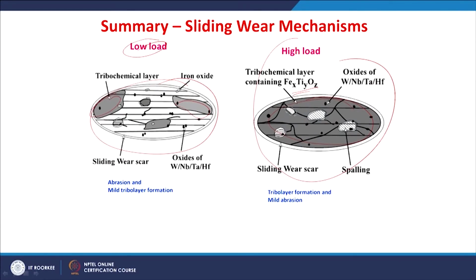So, the process is like this: in the initial conditions of sliding, the deformable material or the nickel binder phase comes out, smears out and deforms, followed by the cracking of these ceramic core and rim phases. So, at lower loads the oxidation or abrasion is dominant; at higher loads, the oxidation of this debris will lead to a compacted layer which is rich with the iron titanium oxide, because it fills the entire surface, and then it reduces further wear from the underneath surface.